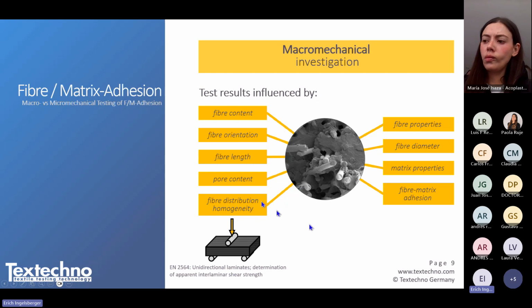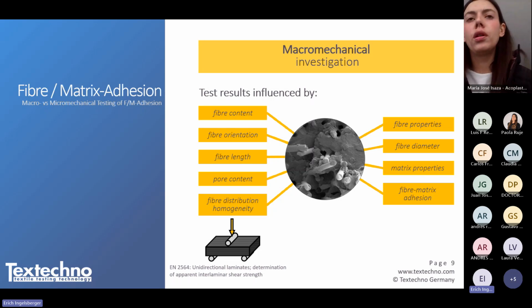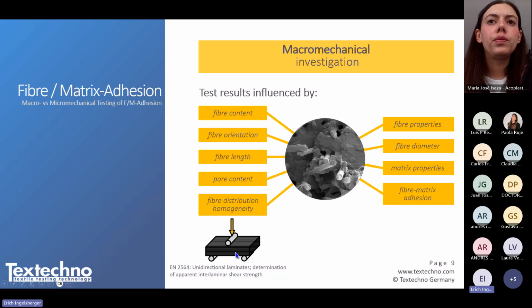For example, the fiber orientation. Here you see all the fibers precisely in perfect alignment, all of them parallel. But if you prepare the sample, which takes time to make, to cure, to harden, then to cut and test it, if the alignment of the fiber is not perfect, this has some impact on the test results.